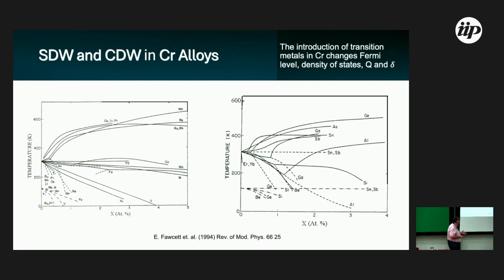Okay, this is a base about the magnetic properties of chromium, but chromium we studied many, many years, different alloys. This is a phase diagram, a complete phase diagram proposed by Fawcett in the Reviews of Modern Physics. And observe the introduction of different metals, different behaviors. For example, vanadium. When you increase the vanadium concentration in chromium, the Néel temperature decreases linearly and vanishes around 4%. Nickel, iron, manganese, molybdenum, tungsten, cobalt, and other metals, titanium, antimony, is a vast magnetic phase diagram. And putting different concentrations produces change of the density of states, Q and delta.